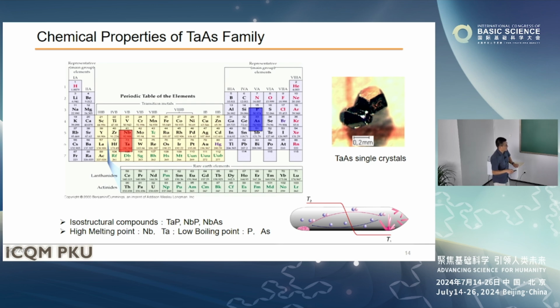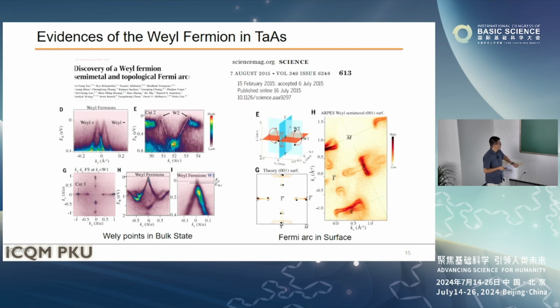And we did that, and found that this is a very successful crystal growth. And this is the first tantalum arsenide single crystal we grew. Although it's very small, we found the mobility is extremely high. Okay, so based on our crystals, our collaborator at Princeton, Professor Hasan, and his group, including Shuang, did some